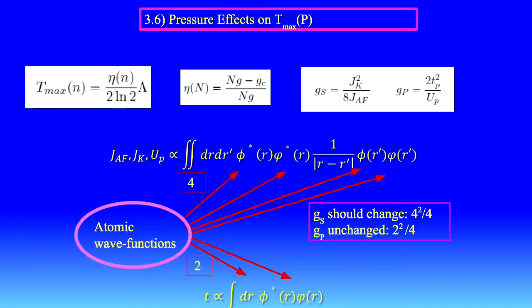So these exchange integrals and the Hubbard parameter are given by these integrals. There are four atomic wave functions, and the hopping parameter has two. Now, since this is t squared over U, this is going to be 2 squared over 4, which is 1. So no effect on the T star. This is a prediction of our model. But in GS, you have 4 squared over 4.